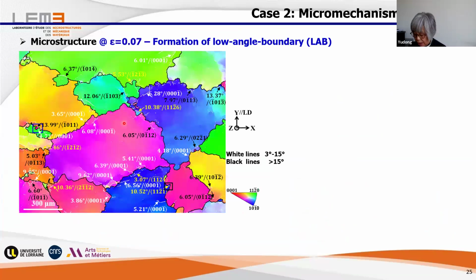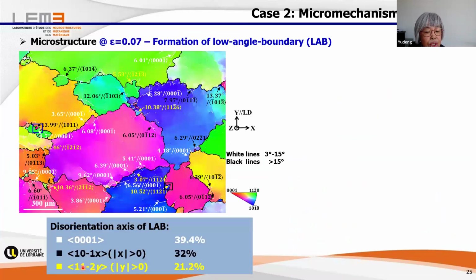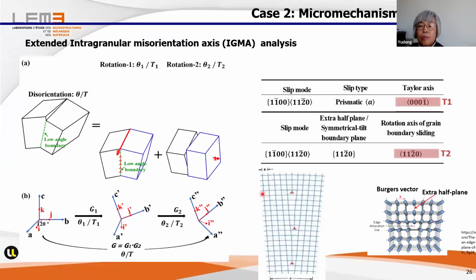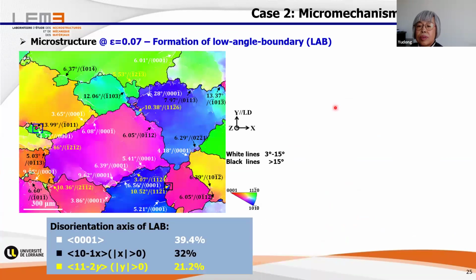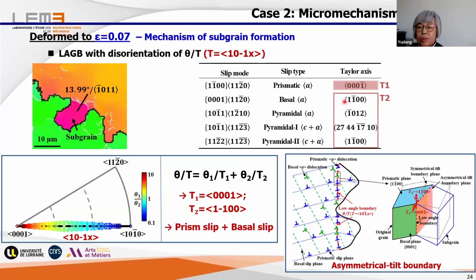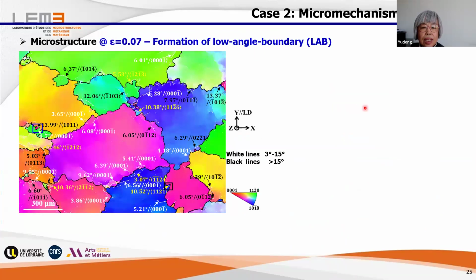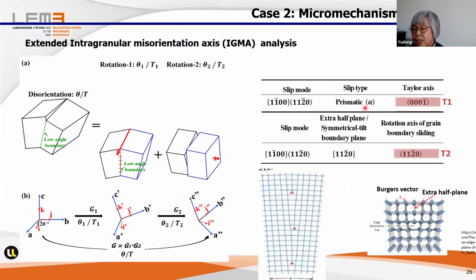And now we have a second case. It is here. Fengming also tried all these possible combinations, but she could not find a fit. And then we enlarged our imagination a little bit. We said, okay, when the dislocations, the prismatic slip, are formed, and then we have this climbing to form the boundary.